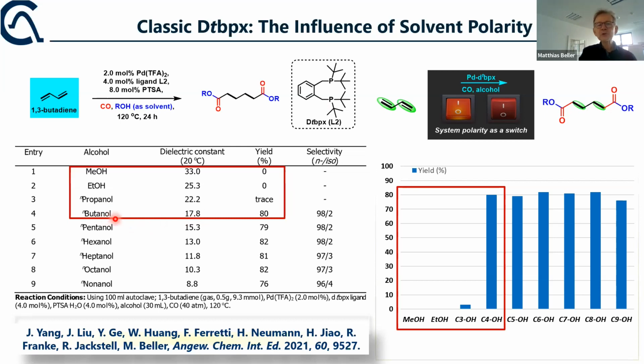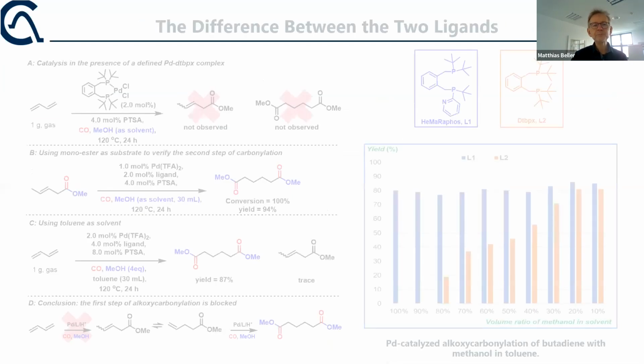However, under the same conditions, when you use butanol, the reaction works very well. And this is a very unusual solvent effect. And we still don't understand completely, let's say, the reactivity switch which we have because of the solvent effect.